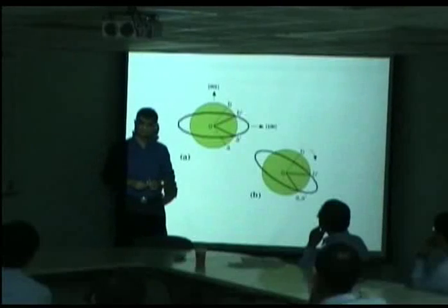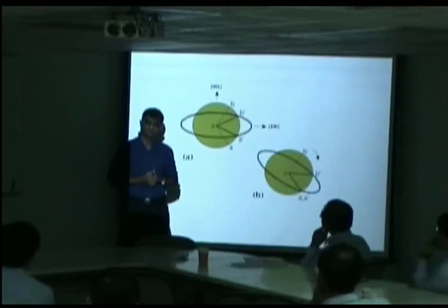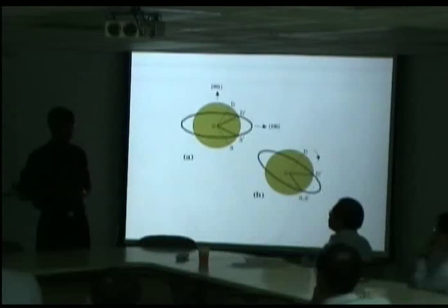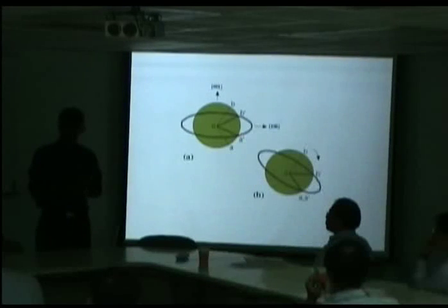So unfortunately, with the Bain strain, there is no line that remains coherent. You can find an undistorted line, but not a line which remains coherent. The Bain strain, you know, it was proposed in 1924, and it is a part of all textbooks, does not produce a coherent line between martensite and austenite.